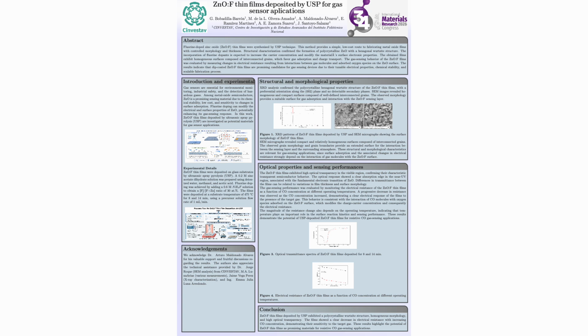For the experimental part, ZnO:F thin films were deposited on glass substrates using ultrasonic spray pyrolysis, or USP. We used zinc acetate dihydrate as the zinc precursor and ammonium fluoride as the fluorine source. The films were deposited at 375 degrees Celsius using deposition times of 8 and 40 minutes.